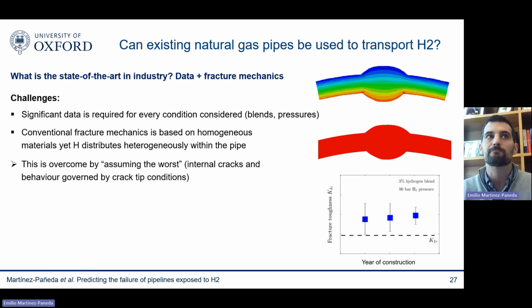So what is industry doing then? Okay, well, basically what they do is they assume the worst, so to say, right? So they assume that the only cracks that matter are the internal cracks, and that leaves a big if, because external cracks can also play a role, and that's something that is an ongoing discussion in the community. And then also they assume that the behavior is governed by crack tip conditions. So basically what they're assuming is that, instead of having this distribution of hydrogen, as it will happen in reality, they assume that the hydrogen is going to be all within the pipe distributed the same as in the inner surface. So, they say, okay, let's be conservative. We're going to distribute hydrogen like this. We're going to assume that our pipe is fully saturated with the hydrogen on the inside. Then we do a lot of experiments, expensive experiments, to quantify the hydrogen toughness for different vintage pipes, different years of construction, and for whatever conditions I'm interested in.